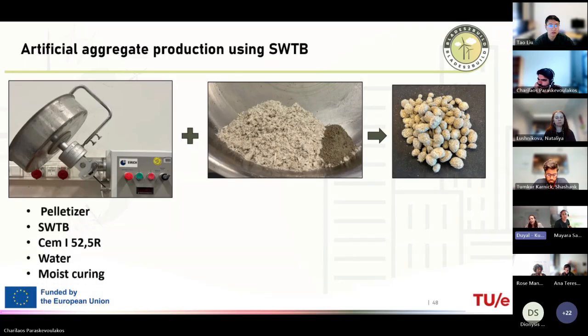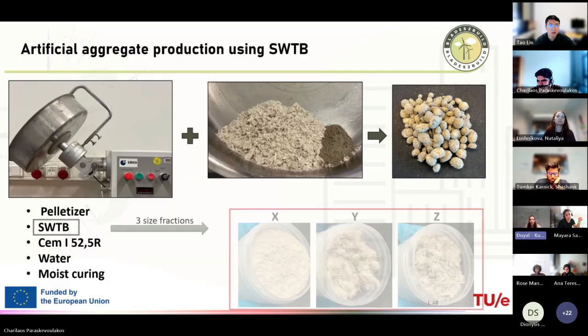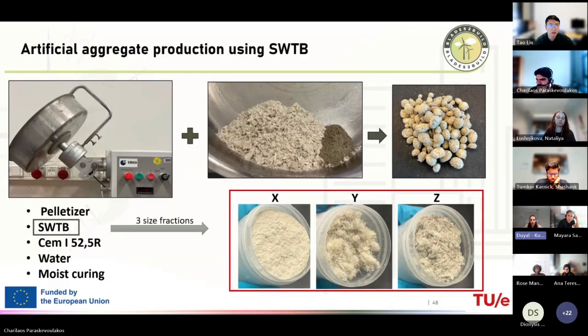It requires a pelletizer, the waste material, the binder, which I use cement, but other binders can also be used, water, and also the curing after the pelletization, which we use moisture curing. I have selected 3 different size fractions. One of them is powder rich, one of them is fiber rich, and the other is almost 50-50 fiber to powder. And I also used 3 different cement dosages.